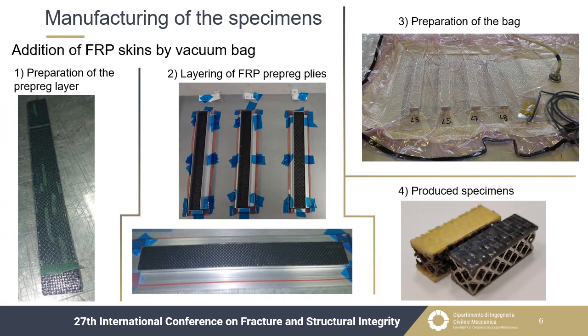The prepreg vacuum bag process was chosen to create the composite skins. FRP prepreg plies were prepared and layered on the mold, together with the lattice core. All the layered specimens were covered with the release film and the breather fabric. Then the mold was closed with the vacuum bag. After the vacuum was drawn, the mold was positioned in the autoclave for the curing process.